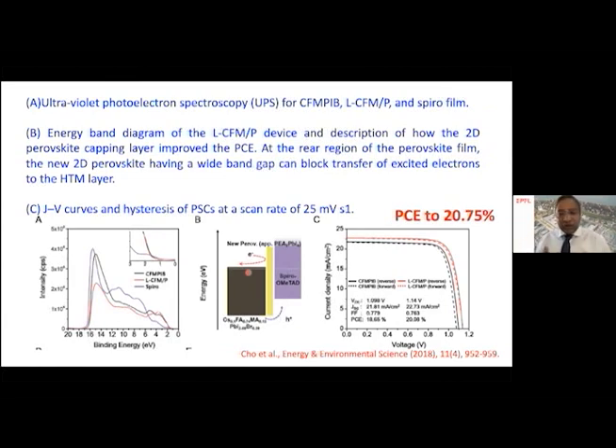So how do we know that this is working? If you look at the reference sample, that gives you 1.09 volts. And with your two-dimensional perovskite, as a layered perovskite, that gives you 1.14. So even though the difference in the VOC is small, it's significant to claim that we have reduced the recombination at this interface. Therefore, we are increasing the VOC.